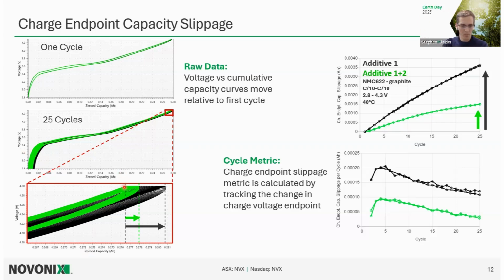And so what we can do is put a pin in the map after our first cycle and then track how fast our voltage curve moves across that x-axis. And that's going to be proportional to the rate of these additional reactions happening, these slippage-based mechanisms. And we can make this semi-quantitative analysis of that rate of reactions. And if you have a cycler that's capable of doing accurate and precise enough measurements, this is a really useful new cycle metric.